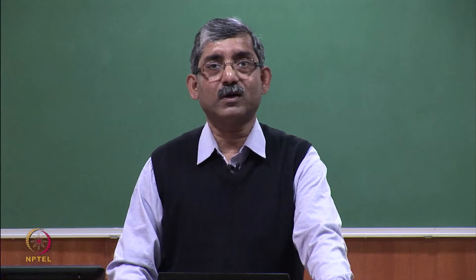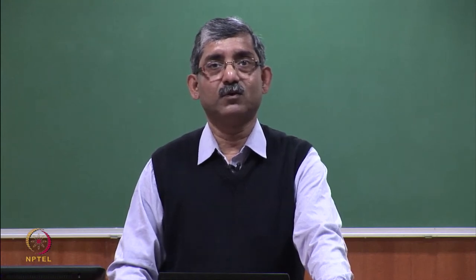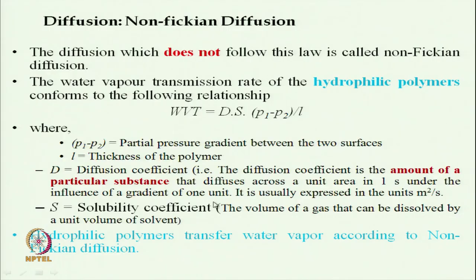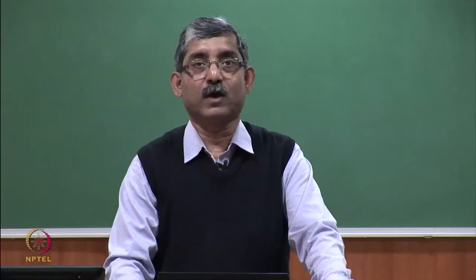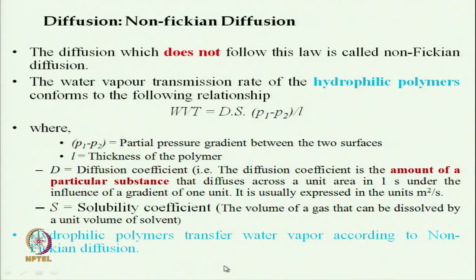So, water vapor transmission is equal to D S (P1 minus P2) divided by L, where D is the diffusion coefficient, S is the solubility coefficient, P1 minus P2 is the partial pressure gradient between two surfaces of the fabric, and L is the thickness of the fabric. Here you will see this is the solubility coefficient. In case of textile material, it depends on the absorption capacity of the moisture vapor. So, hydrophilic polymer transfers water vapor according to non-Fickian diffusion.